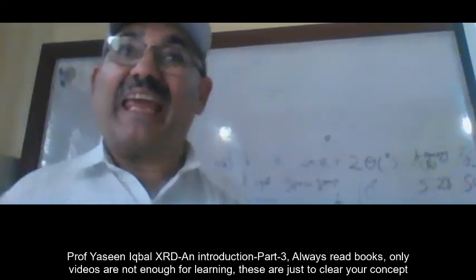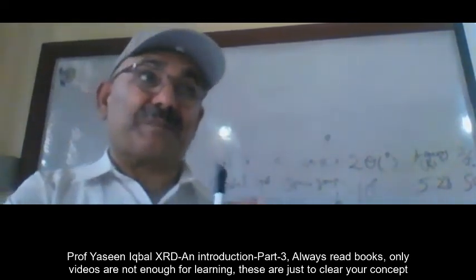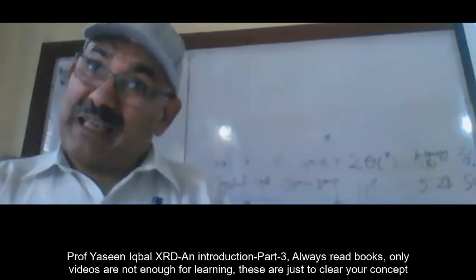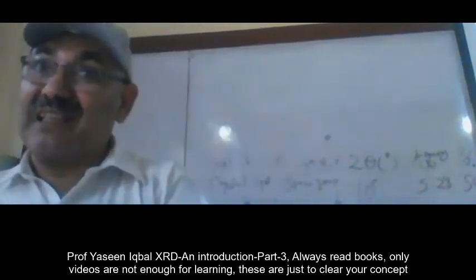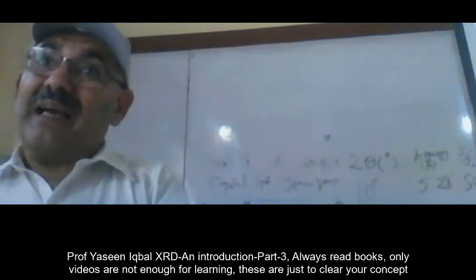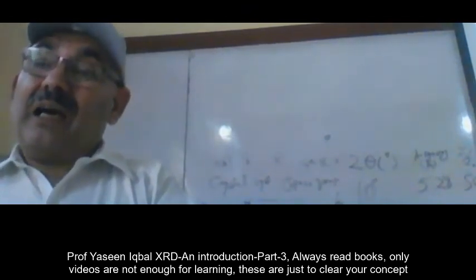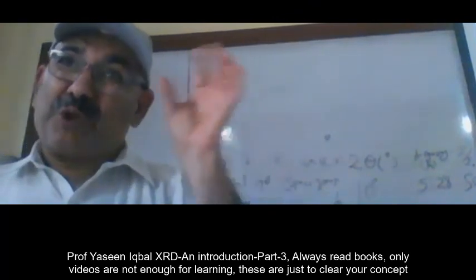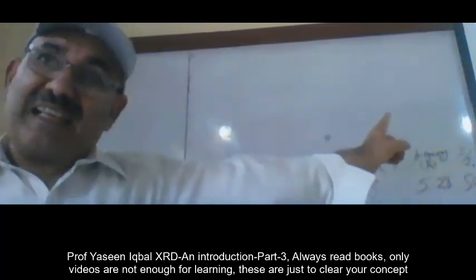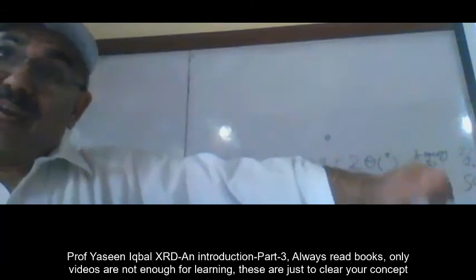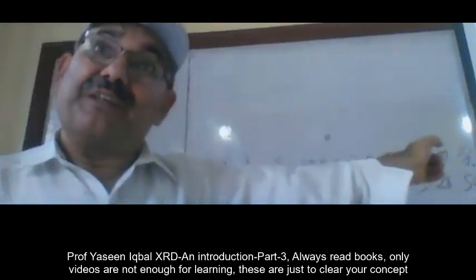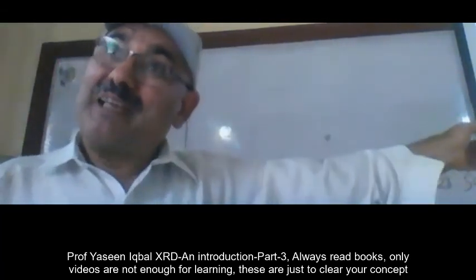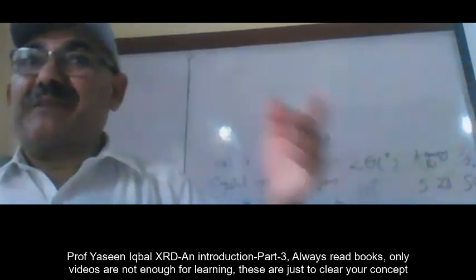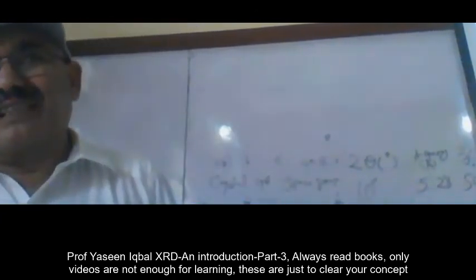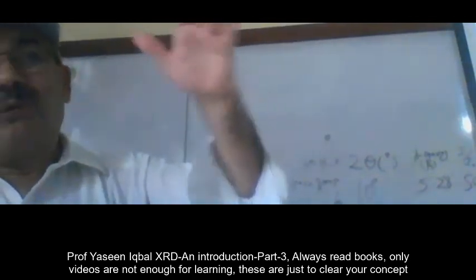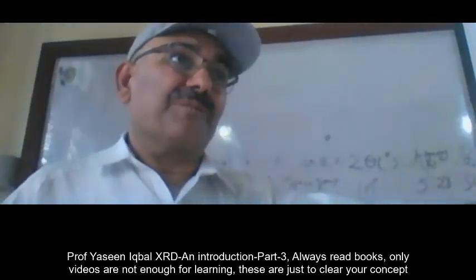So you are not saying that only the interplanar spacings were matching, but the interplanar spacings as well as the intensities. And make sure that the 100 intensity cannot become 50 and the 50 cannot become 100. But the 100 will always be 100, and the 50, 40, 30 or lower intensities can slightly go up and down, but they must be proportional.